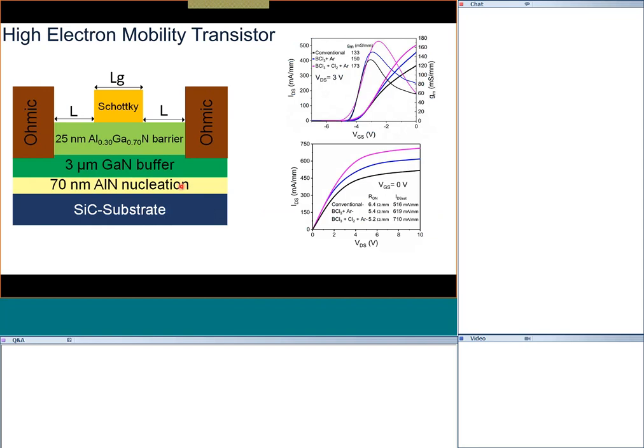Looking at the cross-section of a gallium nitride based HEMT: we have an AlGaN barrier layer, which is the high band gap material — larger than gallium nitride. Gallium nitride is the smaller band gap material. Aluminum gallium nitride is the large band gap material, gallium nitride is the small band gap material. There are layers beneath — a simplified aluminum nitride nucleation layer — which are important to have very high quality material for the transistor. The quality of the GaN layer largely depends on what layers are beneath it.